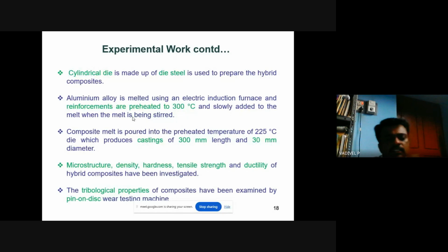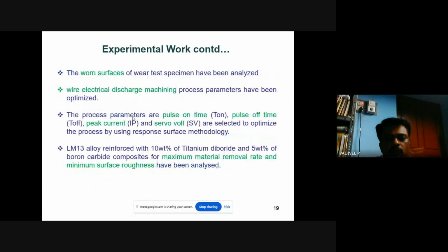And also the tribological properties of the composites have been examined on the pin on disc wear testing machine. The wear test of the machined material is done using the pin on disc apparatus. Worn surface of the wear test specimen, the machined surface, is analyzed by using the SEM.